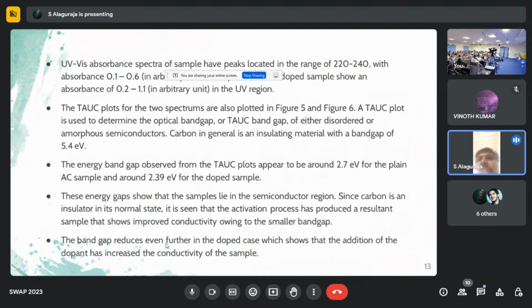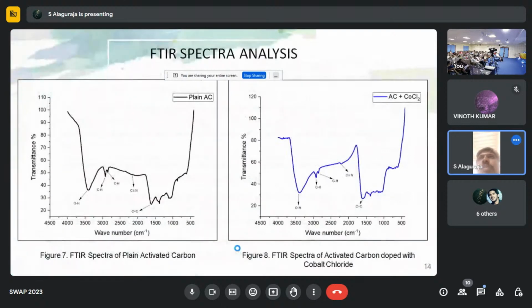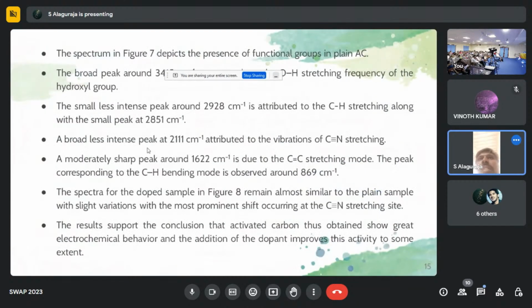The band gap reduces even further in the doped case, which shows that the addition of the dopants has increased the conductivity of the samples. From the FTIR spectrum, the small, less intense peak around 2,928 per centimeter is attributed to C-H stretching, along with the small peak at 2,851 per centimeter.